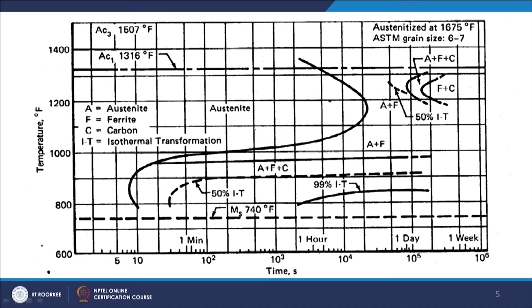If the steel is exposed at 950 degree centigrade, then it will be quickly transforming into the phases. So, the time is not much for rejection of the carbon from the austenite which is being formed into ferrite, and that is why we will see that fine grained low carbon martensite is formed, apart from the formation of the ferrite and the fine bainite or lower bainitic structure. So, in these cases mostly we get the ferrite, the lower bainite and the low carbon martensite, which offers a very good combination of the mechanical properties.